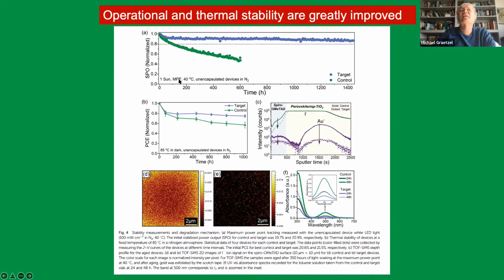So the cell is held under maximum power point condition. It delivers power all the time, the maximum power it can deliver. And it's held at 40 degrees in addition to the temperature stress. And so you can see the target is with the thiophene derivative. There's hardly any degradation, say less than 10% or maximum 10% over 1400 hours continuous illumination. And so that's very impressive.